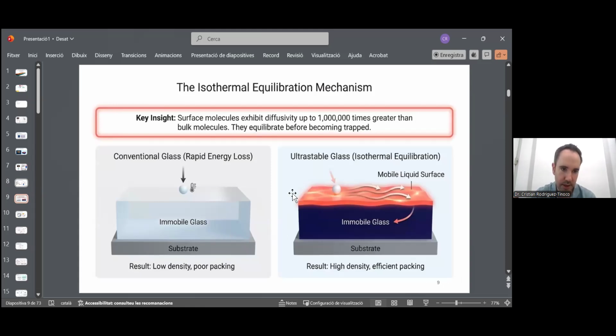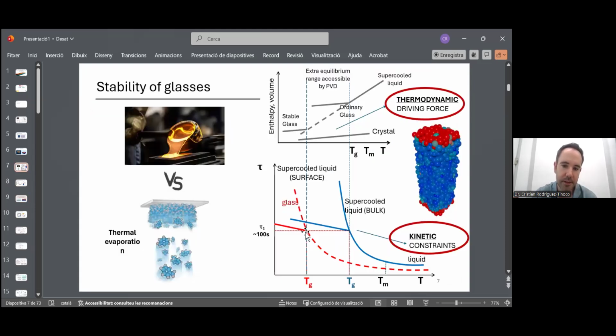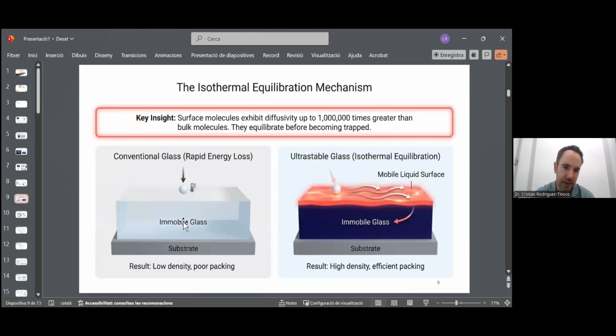Again, this is not the same everywhere, so let me go backwards. Eventually, even this surface relaxation time will be larger than the experimentally available relaxation time. So if we continue going down and down in temperature, even this new methodology to prepare a glass will fail. We will not be able to keep the system in equilibrium down to infinitely low temperatures. Of course, if the substrate temperature is too low, very, very cold substrates, then the molecule that gets to the surface will immediately lose the energy, and then we will get again a very unstable glass.